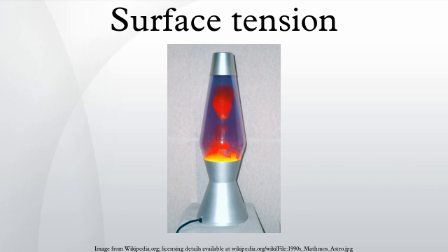This means that although the difference between the liquid-solid and solid-air surface tension is difficult to measure directly, it can be inferred from the liquid-air surface tension and the equilibrium contact angle, which is a function of the easily measurable advancing and receding contact angles. This same relationship exists in the diagram on the right. But in this case we see that because the contact angle is less than 90 degrees, the liquid-solid minus solid-air surface tension difference must be negative. Special contact angles.